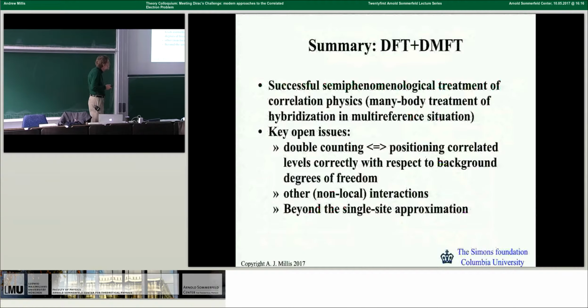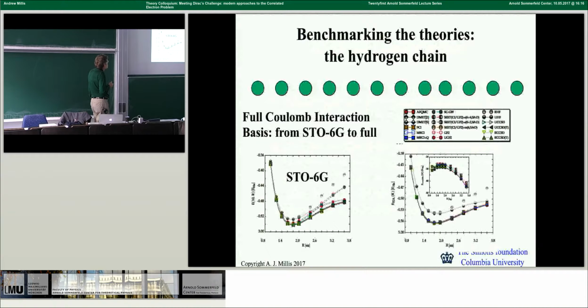All right, so to start to get our hands around this, I'll just say in the last 2 minutes something else we've been doing very recently. We've taken sort of the simplest possible realistic theory, in this case a chain of hydrogen atoms. In this problem, we treat the full e squared over r Coulomb interaction with all the matrix elements. And you can either do what chemists call STO-6G, which means you just take one orbital per hydrogen atom, or you can just do the full basis, essentially treat the problem in the continuum. We can again ask, how well do all of our different theoretical methods shown here do in computing the ground state energy? And we haven't yet gotten to excitations. That's in the next step. Right, as a function of interhydrogen separation.